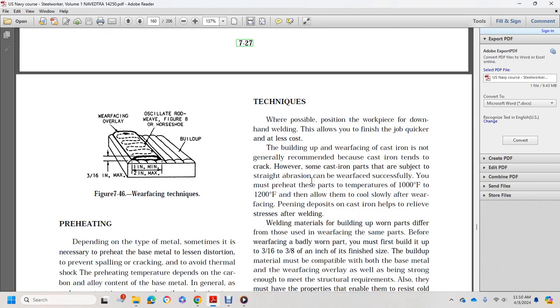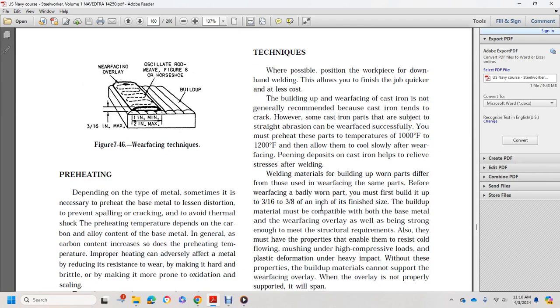Techniques: when possible, position the workpiece for downhand welding. This allows the job to be finished quicker and requires less build-up of the wear face. Cast iron is generally not recommended for wear facing because of its tendency to crack. However, some cast iron parts subject to straight abrasion can be wear faced successfully. Most must be preheated to a temperature of 1,000 to 1,200 degrees Fahrenheit. Allow them to cool slowly after wear facing. Peening deposits on cast iron helps to relieve stress after welding.